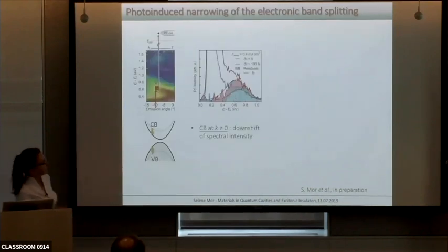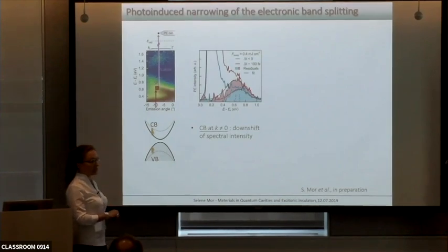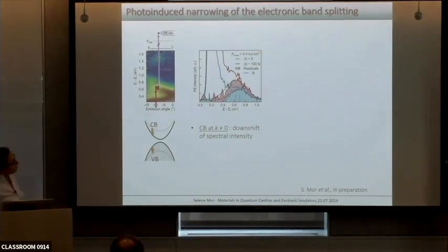And to do this, which is what you were asking before, we perform this kind of experiment, photo-exciting electrons into the conduction band and photo-emitting them with a second probe photon pulse. In this case, which is the pump energy used? It's still 1.55 eV, the same as before, so 800 nanometers. This pumps from just below the valence band into the conduction band.